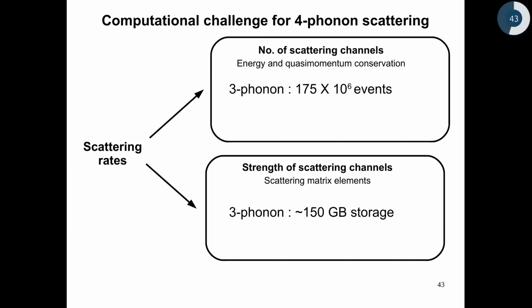So if you look at a typical conventional approach calculation, that is calculation involving 3 phonons for a reasonable grid, I think these numbers are for a 21 cube grid in the Brillouin zone. You typically have about 100 million scattering events of 3 phonon processes, and to calculate and store the strength of these events, you typically require 150 gigabytes of storage. These kinds of numbers are very doable these days. You can get this work done on a single compute node in a matter of a couple of hours.